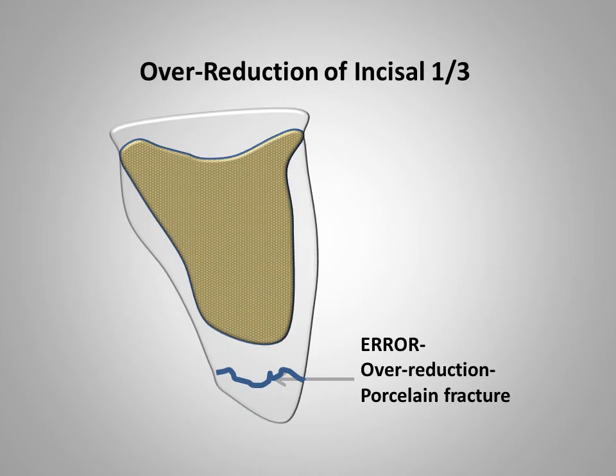This slide illustrates over-reducing the incisal surface to ensure adequate translucency in this area. The shortness of the preparation decreases the retentive qualities of the crown, and an area of unsupported porcelain is likely to fracture. It has been observed that in any stress-bearing area, porcelain in excess of two millimeters is liable to fracture. So in order to prevent a fracture, one would have to extend the coping longer, which defeats the purpose of over-reduction of the tooth. Using depth guides to establish the reduction, along with a putty reduction guide, is useful to prevent this type of error.